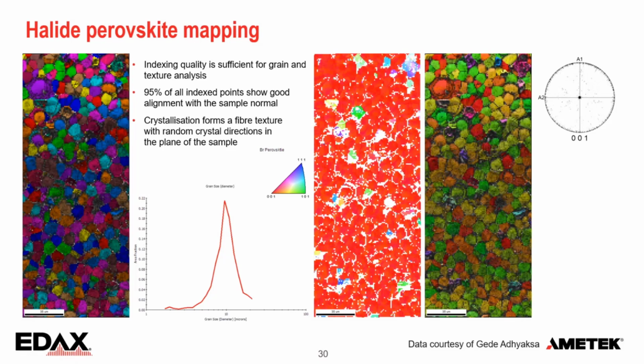This is at about 10 kV, 200-300 picoamp, and 100 millisecond exposure. So that's what we needed to get good data. And then on this film material, we could get here in this red map, that's the IPF map. So it's a fiber texture, as you can see here on the right. Almost all the grains have the C-axis aligned and the other axis distributed around the edge of the pole figure.